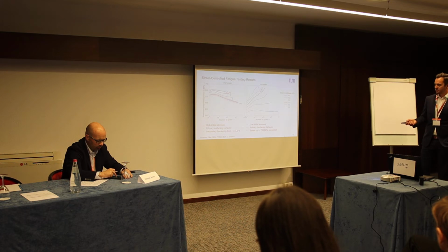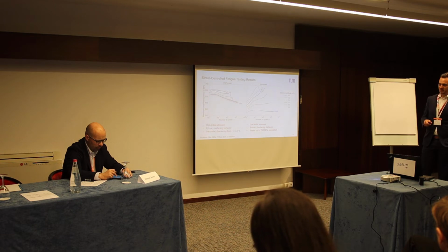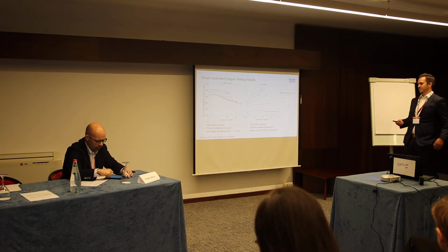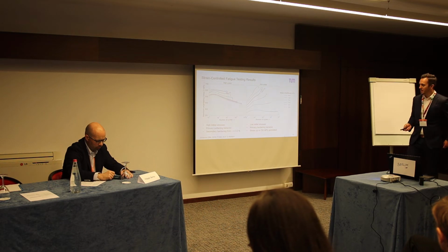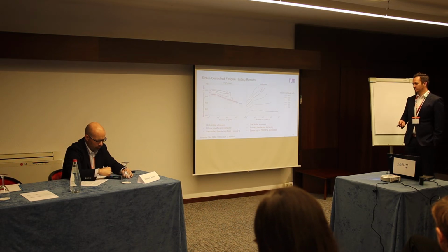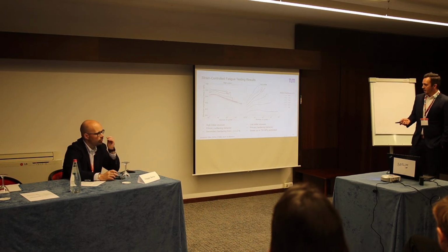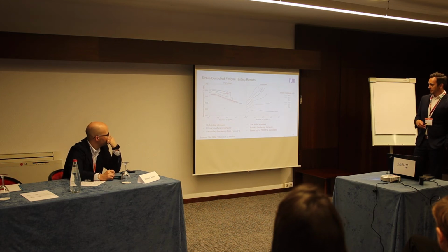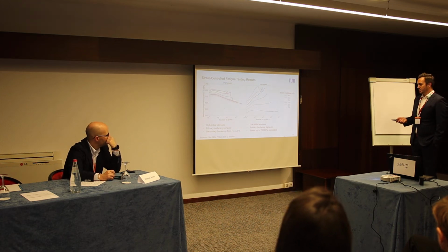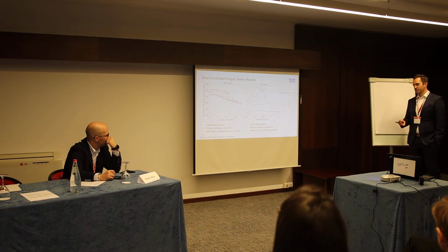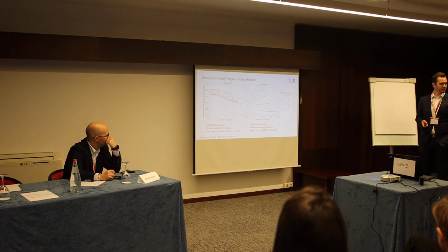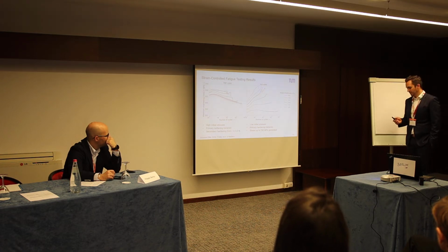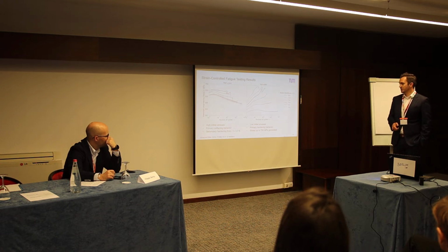Only from 2.5% strain amplitude did we see a little bit of secondary hardening. You could also call the first effect primary hardening, but I think it's more of a softening overall, so I call it primary softening behavior. On the hot roll 316L, however, it looks completely different. We have low initial stresses, and we have a primary hardening behavior overall. Also, stresses of up to 700 megapascal were generated during the testing.